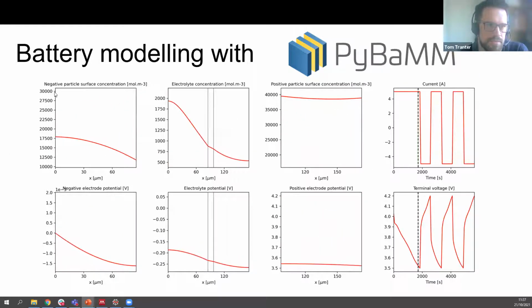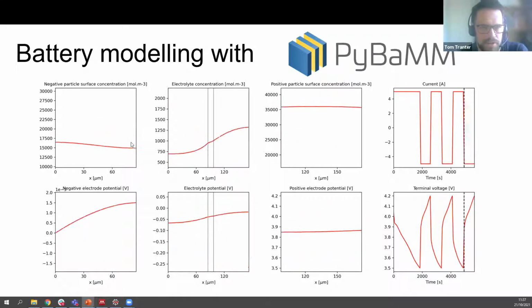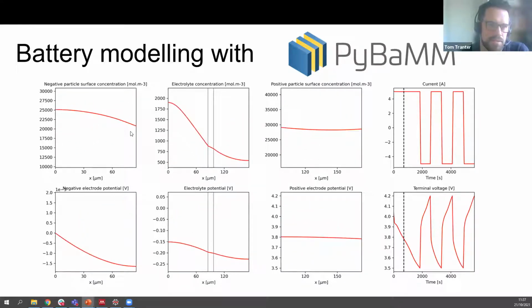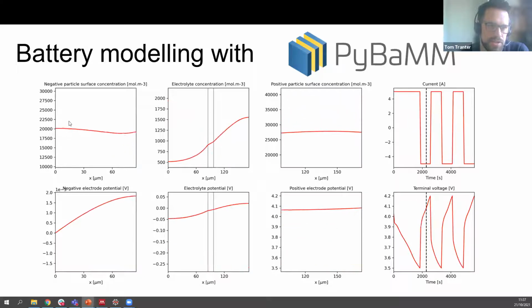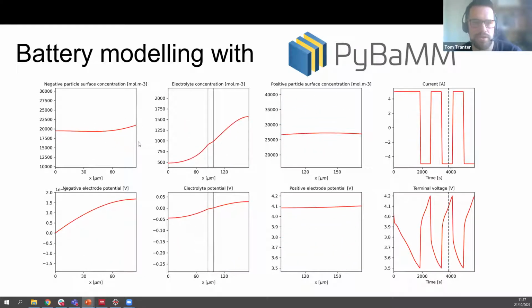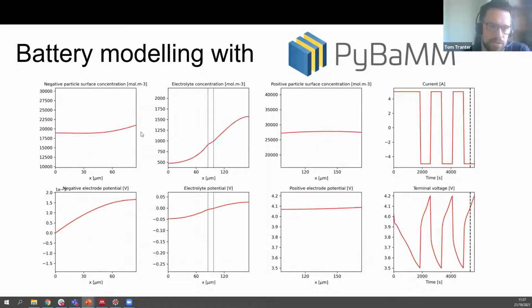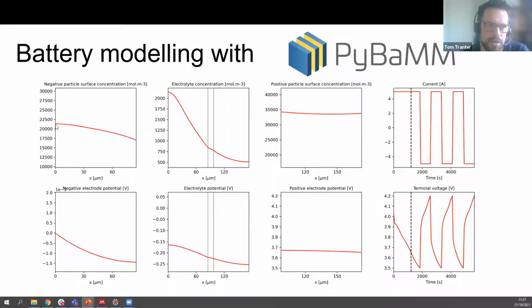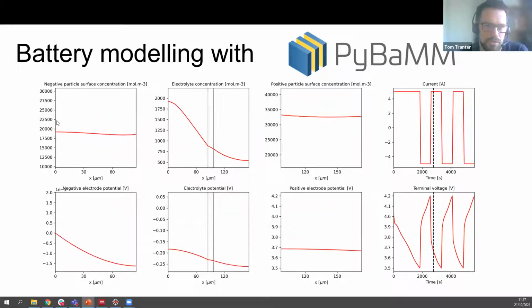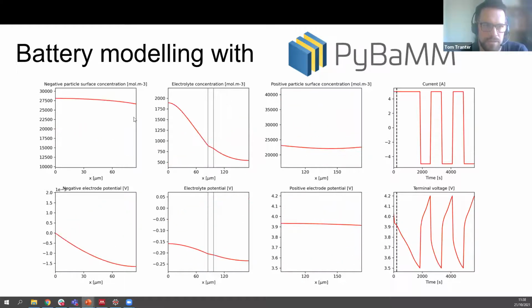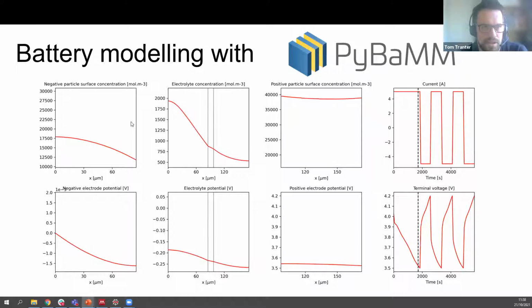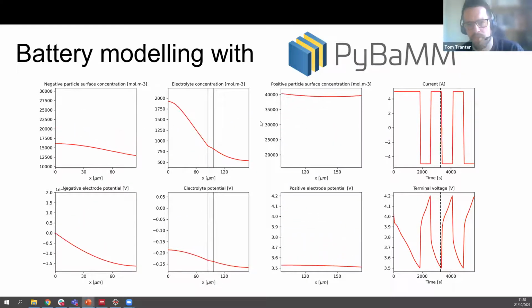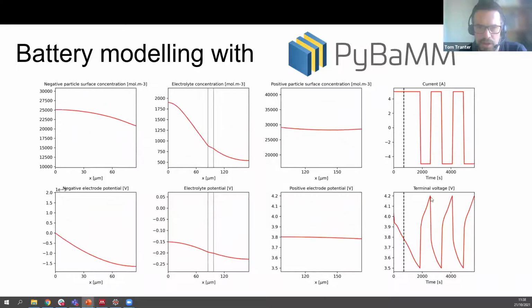This is cycling up and down, and this spatial variation in the x direction is essentially due to the transport limitations within the pore space itself. So if ions were able to move very freely about the cell, you'd expect these to be sort of more flat lines. And that's what our reduced order models end up predicting. We don't actually resolve this concentration in the x direction with the simpler models. But you can see here the voltage of the cell cycling up and down.